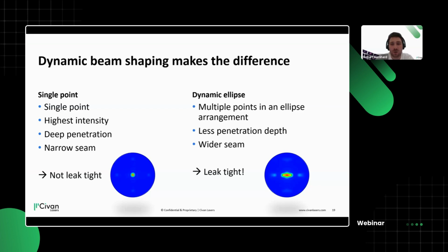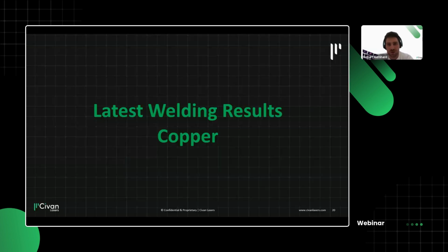And we get, with this dynamic beam shape following the path of the weld, leak-tight coolers at 500 millimeters per second. This is something we weren't able to achieve before, and to my knowledge no one else was able to achieve this high speed without cracking in other typical Gaussian configurations. This is also a nice thing about the scanner, where the process speed is not limited by any axis, and this is something we can do with our laser as well.